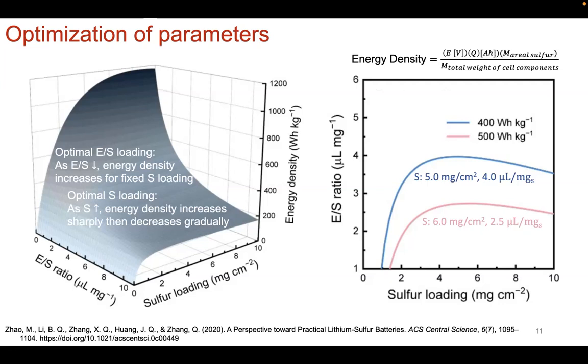So where do we need to be? What are our targets for engineering these types of electrodes? Where we need to be is basically at 400, 500 watt-hour per kilogram to be competitive for electric vehicle applications. So what that really means is we need to be able to engineer electrodes that perform well, that cycle well, have high cyclability, high rate capability, and the mass loadings are relatively high. So these numbers are pretty typical: 5 milligrams of sulfur per centimeter squared of the electrode area, moving to 6 milligrams per centimeter squared, and even leaner operations of electrolyte to sulfur ratio. So that's where we really need to be to be competitive.